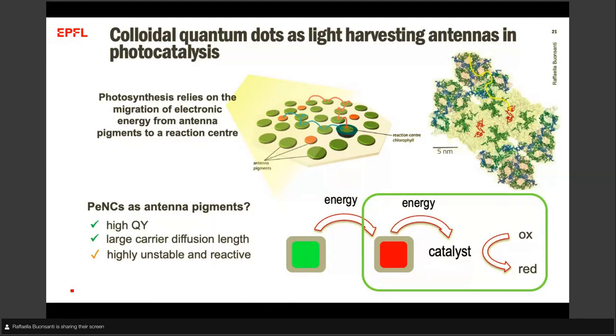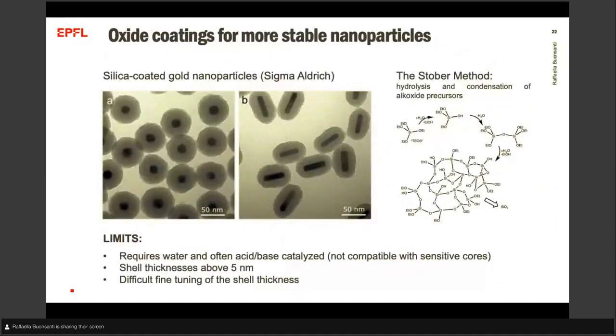Now, having assessed that we can do this transfer and we can drive a reaction, we wanted to explore energy transfer between quantum dots in the presence of the spacer. However, we also wanted to switch back to our beloved solution, because we do love to work with inks and with solution, which gives us more flexibility in terms of the techniques that we can use and the substrates that we can use for devices. And so we wanted to grow at this point an oxide shell, but in solution. When we think about oxide coatings on nanoparticles, the most common coating is silica. You can buy silica-coated gold nanoparticles from Sigma Aldrich.